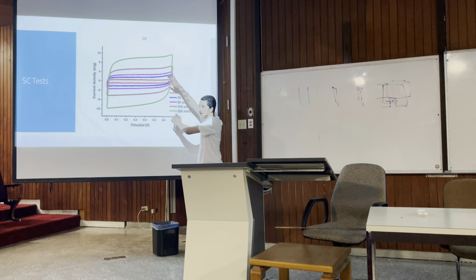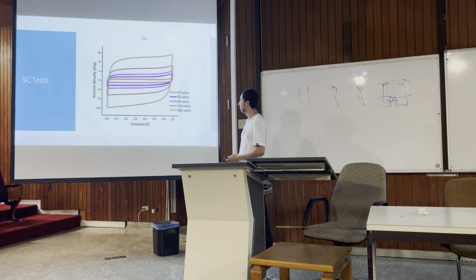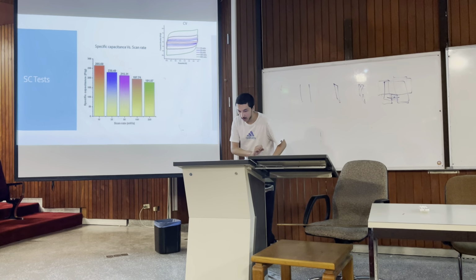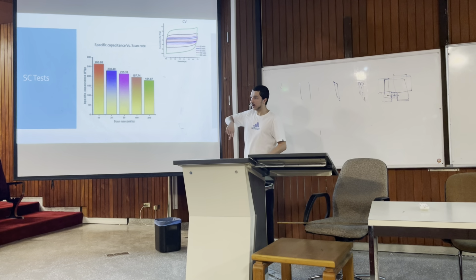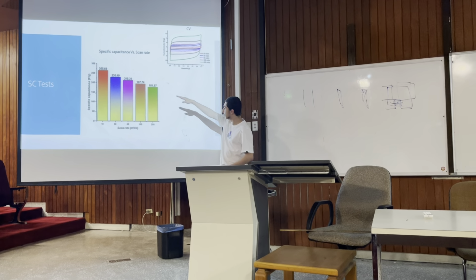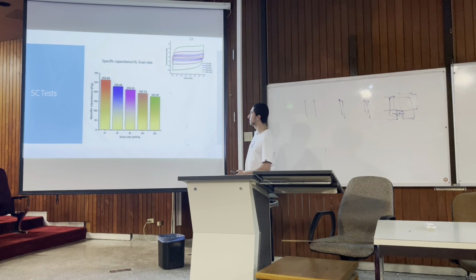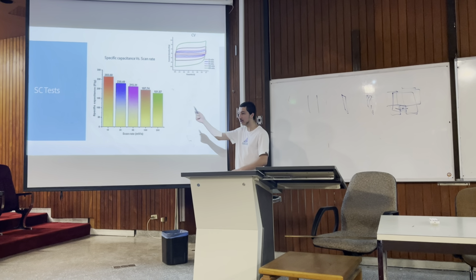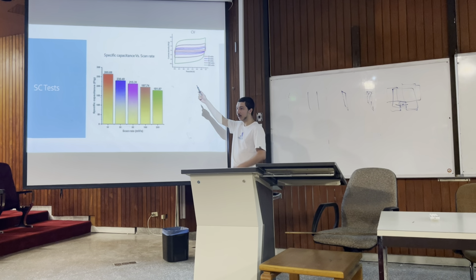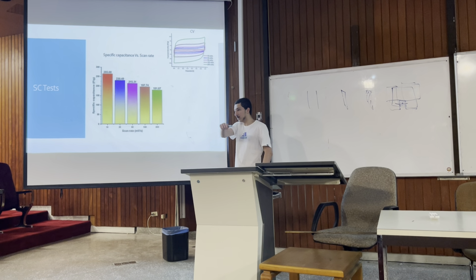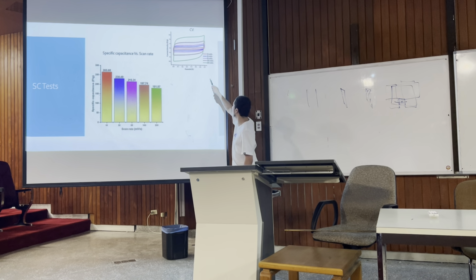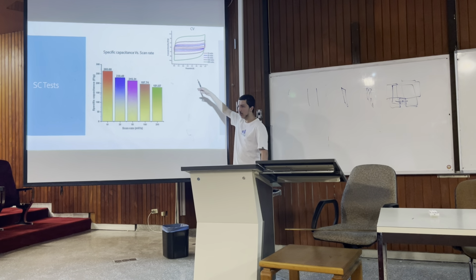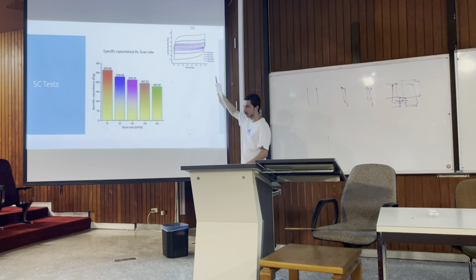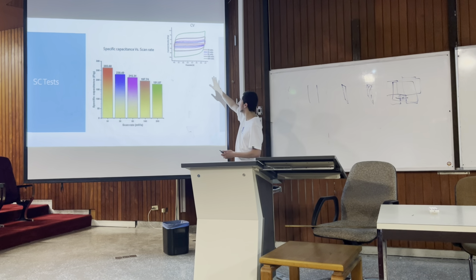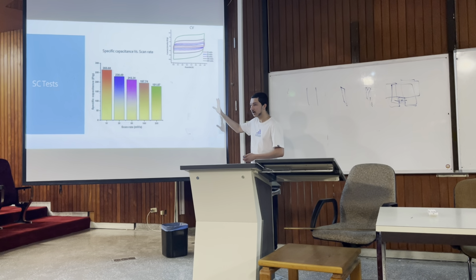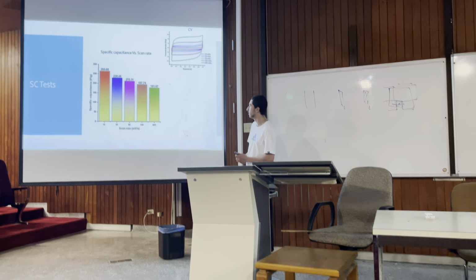increased area. And then when we find the area divided by dV over dt, we get a decreased specific capacitance per scan rate, which shows an inverse relationship, which is what we had in the equation. We had area over potential window, which we fixed constant to 0.7. We went up to 1.5, but we got some pretty weird results. So we kept it constant at 0.7, which is pretty standard in the literature.